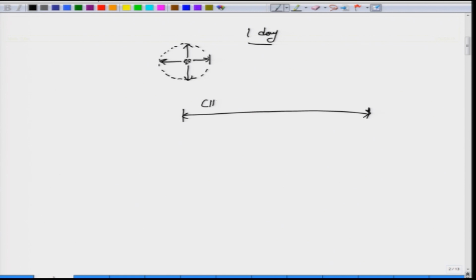So, let us say if we have an ensemble of particles accumulated at a point and we let all the particles diffuse and observe how much diffusion has progressed in a certain time. So, let us say in one day. As soon as we allow the particles to diffuse, the particles will diffuse randomly in all directions, and we track the front as a function of time. So, in one day, if we consider diffusion of methane in air, this front would have progressed about 1.3 meter, whereas if you consider methane in water, this would have progressed only about 1.3 centimeter.